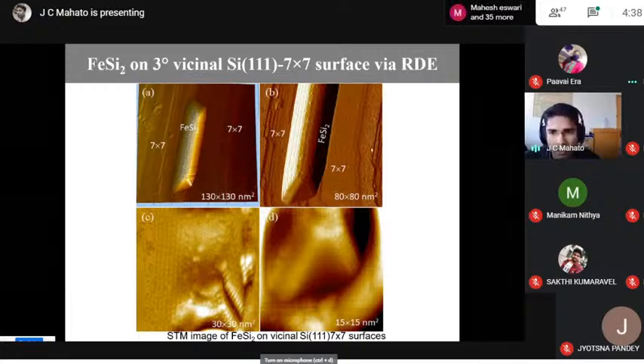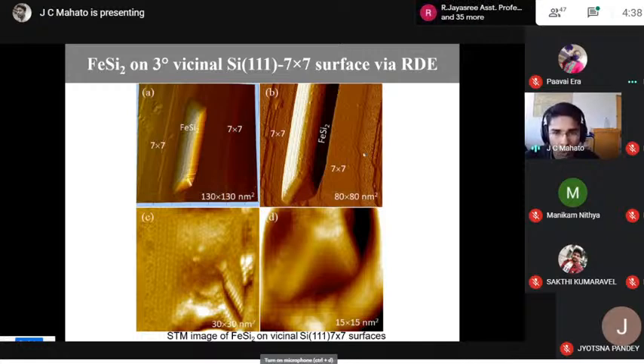And on the silicon surface, we can see from this STM close view that it contains the 7 by 7. The 7 by 7 reconstruction is intact. That means that the iron disilicide grows as an island growth, or Volmer-Weber growth. So our idea was to grow another kind of silicide on top of this iron silicide decorated surface.